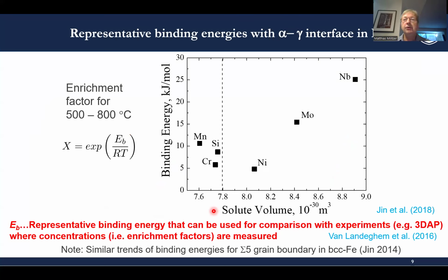And for the austenite decomposition, the temperature range that is of interest is typically 500 to 800 degrees Celsius. One can introduce an enrichment factor that is expressed with a very simple exponential expression, where EB in the exponent is a representative binding energy that is now plotted here as a function of the solute volume. The dashed line is the volume of the iron atom.